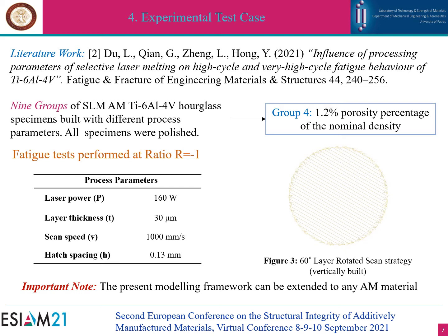The porosity of this group reached 1.2% of the nominal density of the specimen. Fatigue tests were performed at ratio -1, and the process parameters and the scan strategy are presented here. It should be noted that the present modeling framework can be extended to any AM material.